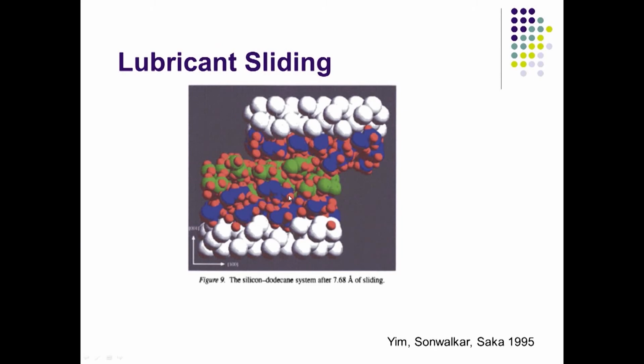With higher shear, the shearing happens on the middle portion of the lubricant. The lubricant has a solid-like structure which is bonded with the top and bottom silicon structures, but if the layer becomes slightly thicker, that means there is a non-bonded part, and then you start losing the lubrication because there is a sliding effect. The sliding effect happens at the middle layer where there are non-bonded layers of the hydrocarbon.